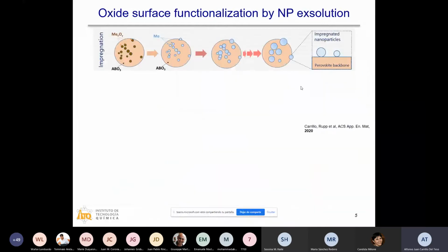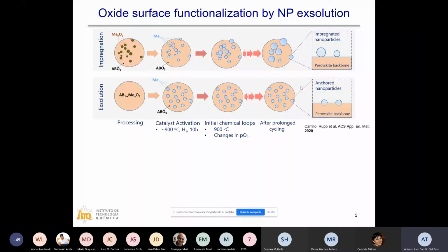Since I'm talking about the incorporation of metals into our oxides, traditionally this has been done by impregnation methods or deposition. Here you put your oxide with nitrates or other precursors, you reduce it, and you will create your metallic nanoparticles. But after several cycles, your particles are going to sinter with neighboring particles, they are going to grow, and their catalytic activity is going to decrease over time. As an alternative, we suggest to use the exsolution method, which has been studied a lot recently in the SOFC community. We thought it would be interesting to apply this concept here.